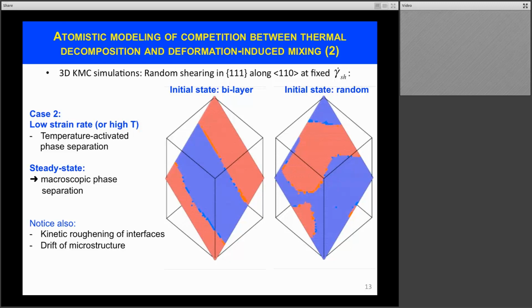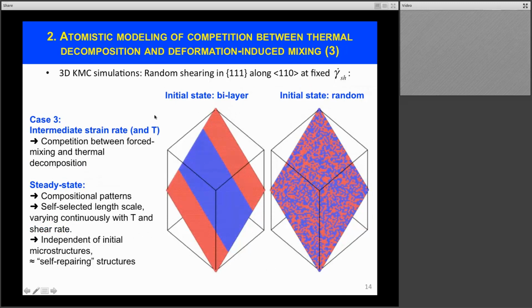So the third case is the more interesting, where now we are shearing this copper-silver alloy, or blue-red alloy, under conditions where the strain rate and the thermal diffusion are of similar strength. And now starting again with this bilayer, what we see is something different. Again, interfaces become rough, but this roughness keeps building up and results in the formation of some ramification of the structure, or refinement of the microstructure. And progressively we are forming a nanocomposite.